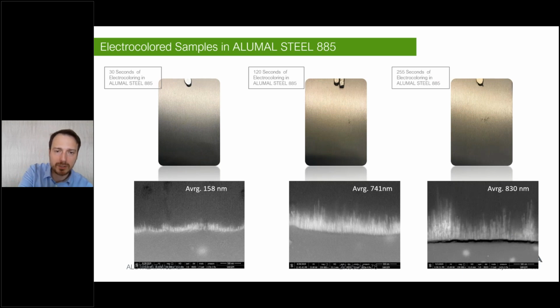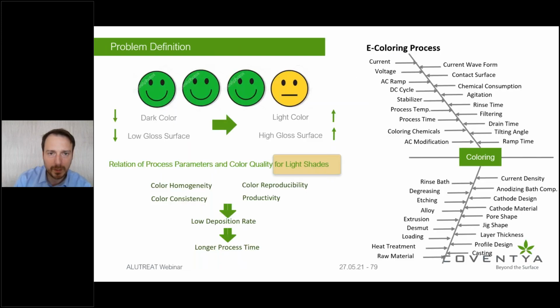the change of thickness, the change of precipitation amount changes, but it changes much more docile, much more controllable. So, of course, I could say that by using the right chemistry, the right surface conditioning, with the controlled anodic oxide cycle, by using the additives, you can meet each color. Well, life is unfortunately not as perfect, and I would be lying if I said it will solve all your problems, but it will at least solve all your problems related to darker shades, even on brighter surfaces. And this approach, this system, where we think about the whole coloring process in conjunction with pre-treatment and anodizing, will give you higher color reproducibility and also a happier lab team.